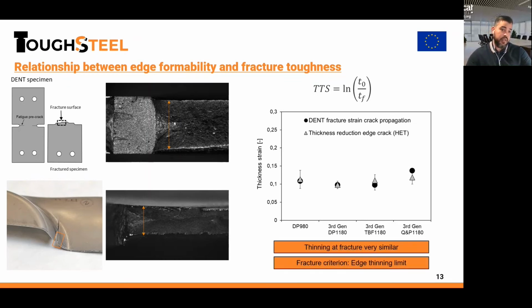So this is further evidence that the fracture mechanisms occurring in both kinds of fractures are pretty similar. But furthermore, this definition of the thickness strain or edge thinning can help to define objective parameters for an edge thinning limit, or edge formability based on this limit, which in the end can be an objective failure criterion to be implemented in modeling, for example. Later, in the next presentation, we will see a little more about how to implement these fracture toughness testing approaches in modeling to predict edge cracking.